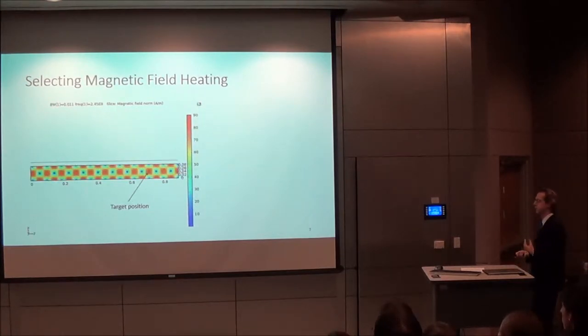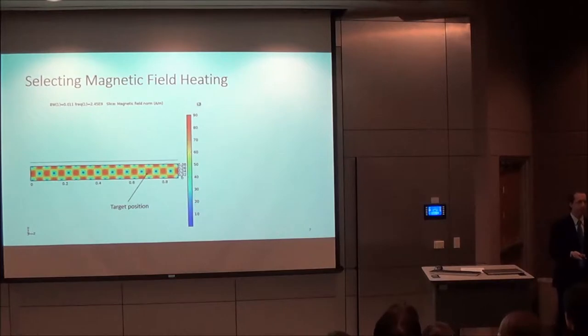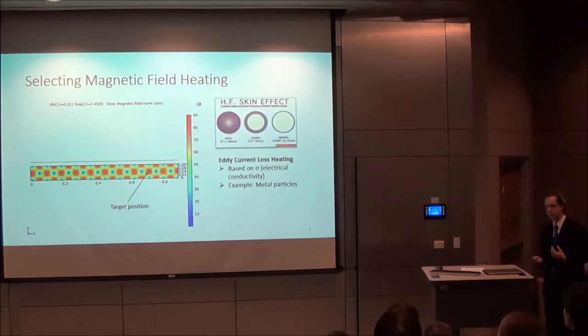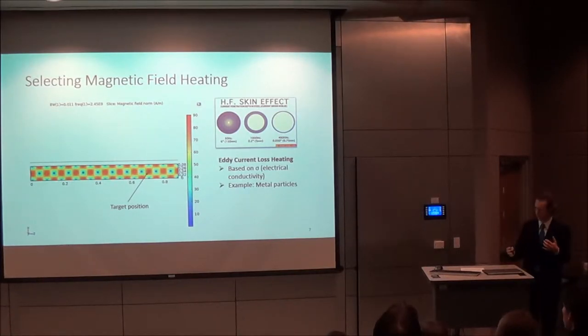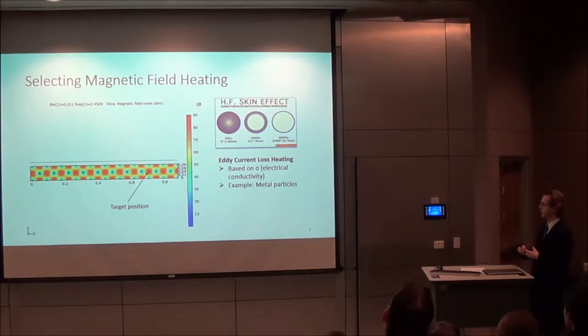In addition, different materials heat via the magnetic field of the microwave, and this may happen through the eddy current loss mechanism, where electric currents are induced on metals and conductive materials, particularly of small size, bulk materials and small size materials, but only when you get to a very particular, small form is the heat, the losses, actually